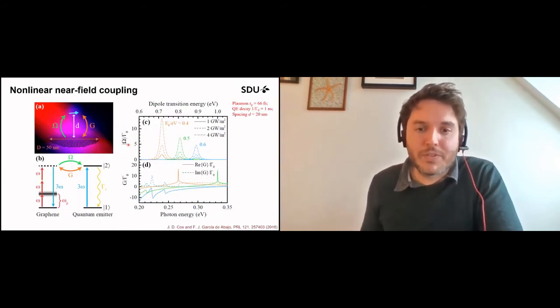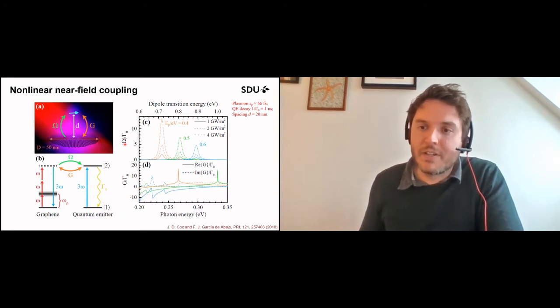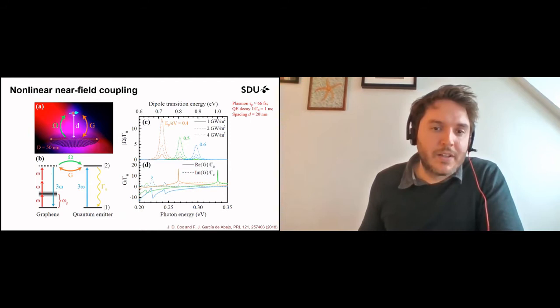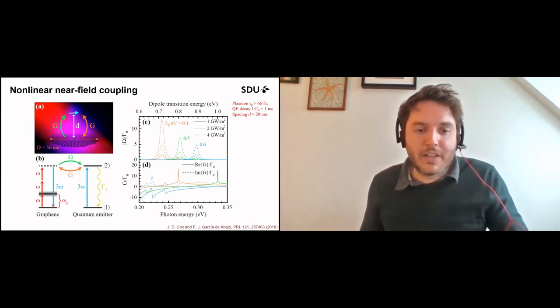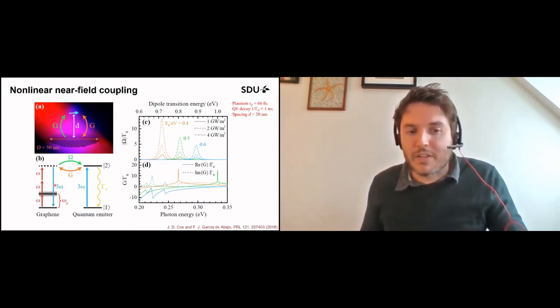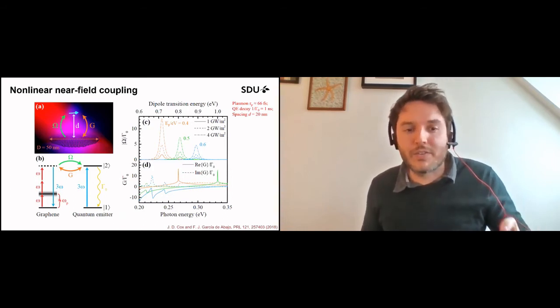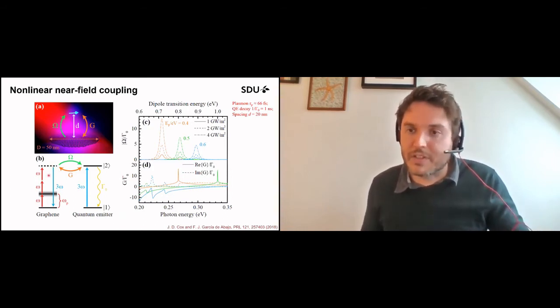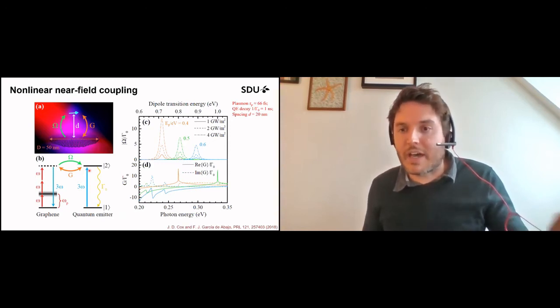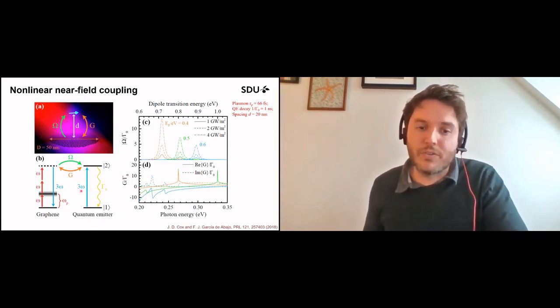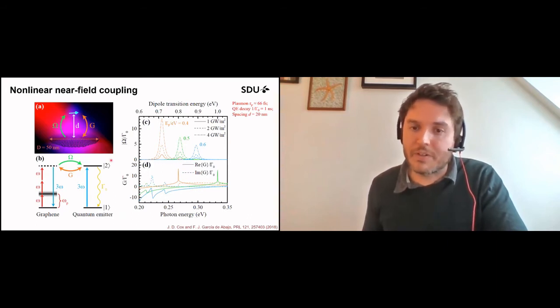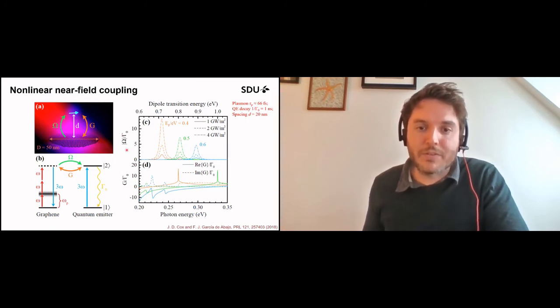There's been a few proposals to use the nonlinear optical response for, say, quantum optical applications. So this is one where I was proposing to actually upconvert light at the plasmon resonance to, say, the third harmonic. And then you can interact the graphene plasmon through this nonlinear process with a quantum emitter that has a resonance frequency at a much higher energy. And then you still maintain the ability to actively tune the graphene, and therefore you can tune the optical properties of your quantum emitter.